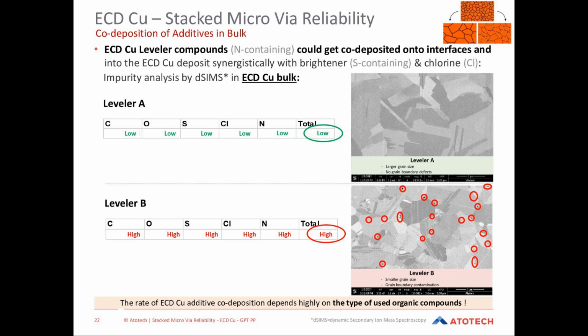And at the grain boundaries, which are partially red circled here, you see impurities, deposits. These are segregations after annealing. So analyzing this copper deposit, you find then for all elements of interest much higher readings. That means here you easily find 5 to 10 times more nitrogen and chloride and sulfur as an example. And this is then a clear indication that here we have co-deposition of the additives, and this is triggered mainly by the used leveler. So the leveler finally is the main additive, which is also then triggering the co-deposition of chloride and sulfur, which are part of the brightener.